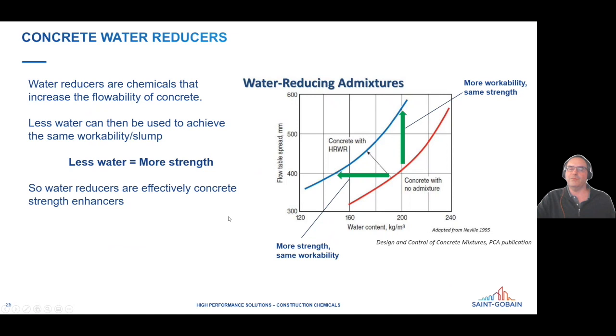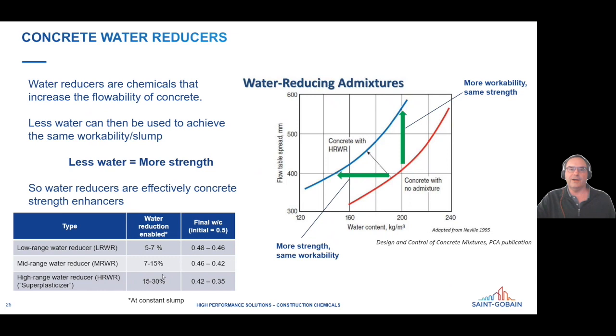So here's just a few types. You'll often hear these terms: low range, mid range, and high range water reducers, with the high range ones also known frequently as super plasticizers. The difference there is just how much improvement in flowability, how much water can you take out. So I think it's useful to look, if you start with a water cement ratio of 0.5, what's the final one? So low range, you get a modest change. With these high range water reducers, really extreme changes in water cement ratio with the same flowability, as far down as 0.35, which is very impressive.